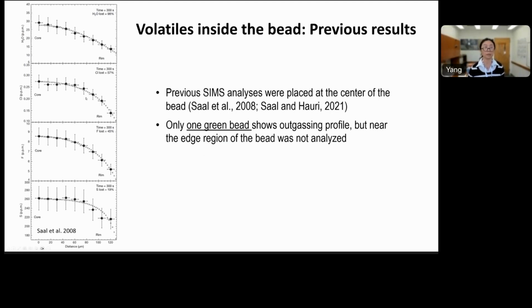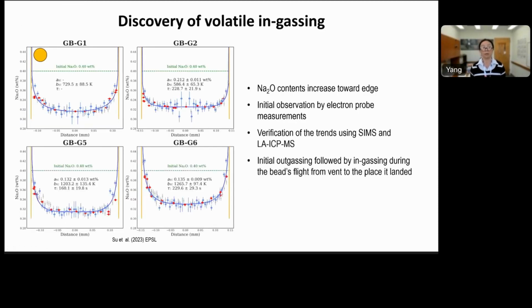2008 shows an outgassing profile of volatiles. But if you examine the figures, the analysis stopped at 10 to 20 microns from the edge, so it didn't go all the way to near the edge. When we looked at the samples with microprobe, we saw that the sodium oxide actually shows an increasing trend toward the edge of the bead. Here are 4 plots from the Su et al. 2023 paper. Orange lines are the physical boundary, the edge of the beads. The gray symbols are EPMA data, electron probe data, the red symbols are SIMS data, and the blue symbols are extracted from laser ablation ICP mass spec mappings.